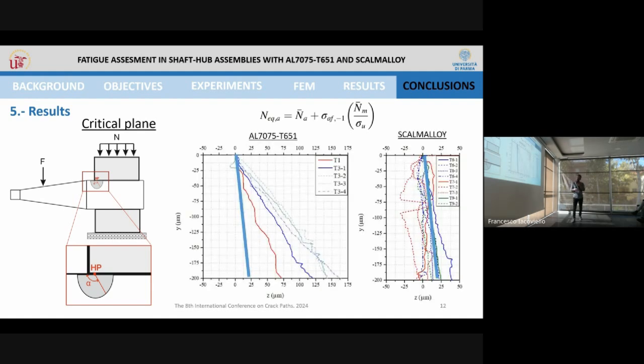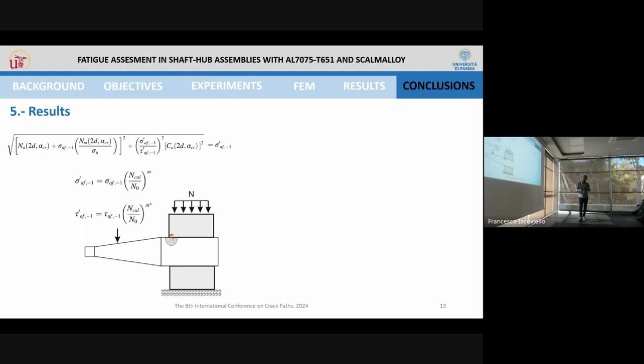So if we compare this estimation with the measurement, we can see on the left for aluminum 7075 that at the beginning maybe the prediction is more or less good, but as we move inside the specimen up to 200 microns it is quite different. On the other hand, amazingly, for Scalmalloy, the predictions are quite good. This is something for which I have no explanation yet, because I was expecting just the contrary: a better result for aluminum 7075, which is a homogeneous material and we have more control on it, and not for Scalmalloy. But this is what I have. I still have to proceed on that. In any case, now we know the orientation of the critical plane, so we move to the life estimation.